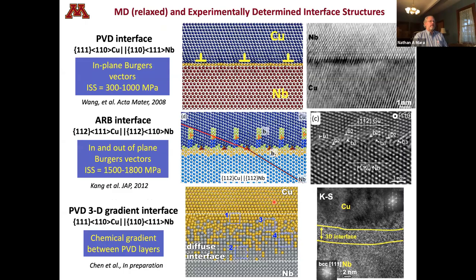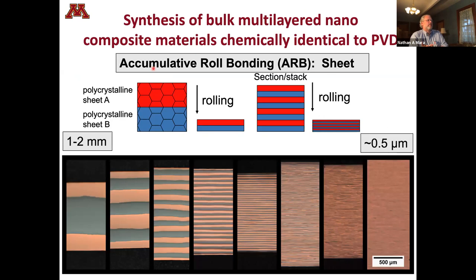So what we're going to do now is move on to this accumulative roll bonded interface. One where we have these in and out of plane Burgers vector misfit dislocation arrays, and also a very high interfacial shear strength when compared to what we just saw. These materials were made at Los Alamos National Lab, and it actually started at Carnegie Mellon with Tony Rollett, who also spent a lot of his career at Los Alamos National Lab before he became a professor there.